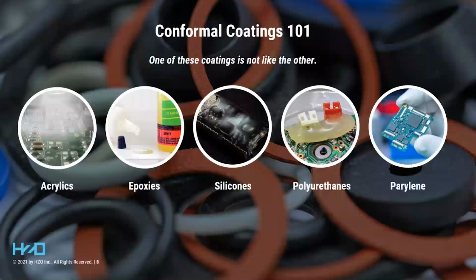Urethanes have many of the same strengths as silicones, but are a little bit difficult to rework themselves. And parylenes. These are the gold standard and the only thin film coating included with traditional coatings and standards over the last few decades. They are lightweight, solvent-free, and these are applied at a fraction of the thickness of traditional materials.